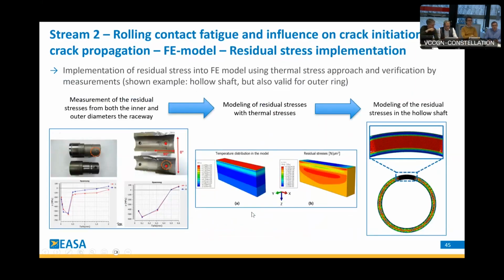We have mentioned already the importance of residual stress. So we implemented the residual stress into the FE model by using a thermal stress approach. And we did measurements for this. And to show you one example, we selected the hollow shaft, but it's also valid for an outer ring. On the left side, you see the cut parts, and you see the measured values for the residual stress. And it was measured from both sides, from the inner and the outer diameters of the raceway. This data is then taken over into the model by thermal stresses, and we end up in the full model, which means we have the ring, and also the loading by the RCF, but also including the residual stress.